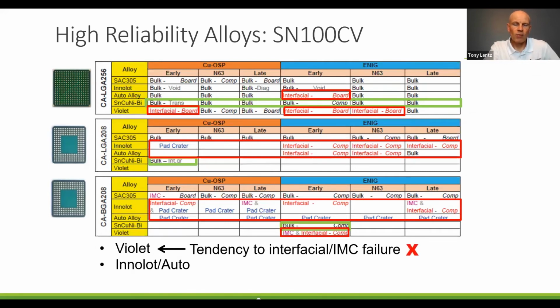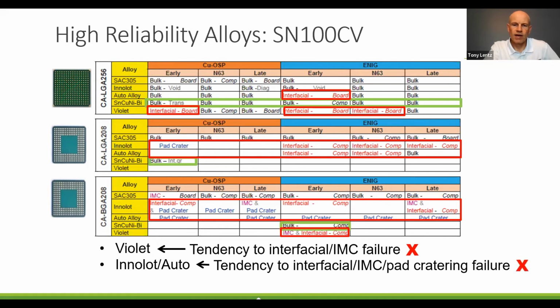Innolot and another automotive alloy tended to have interfacial IMC failures as well as pad cratering. So Innolot and the other auto alloy were pretty strong alloys, almost too stiff. And so during thermal cycle testing, they tend to rip the pad right off the board. And that's not desirable. Or interfacial IMC failure is also not desirable.